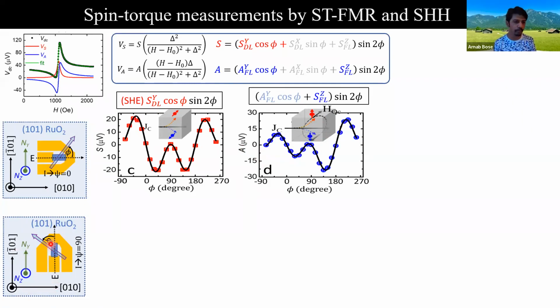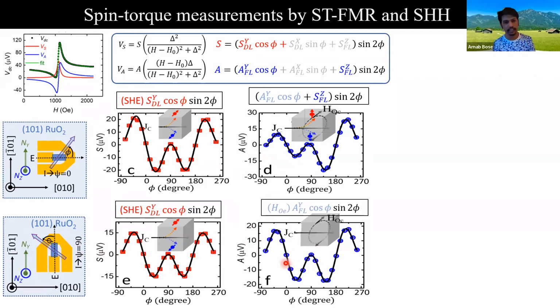In contrast, when we do the measurement for this direction, psi equal to 90, we find everything is standard. Both symmetric and antisymmetric components show the angular dependence cos phi, sin 2 phi, meaning here we have regular spin Hall effect, and here we have a regular Oersted field.